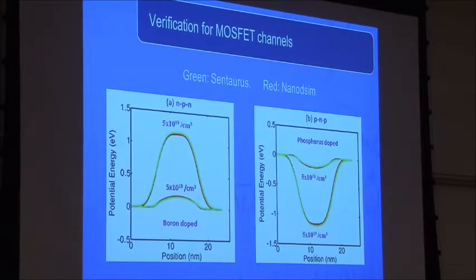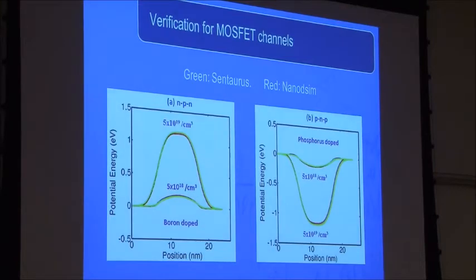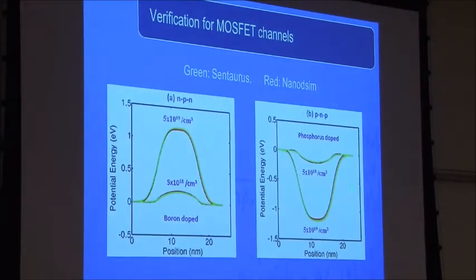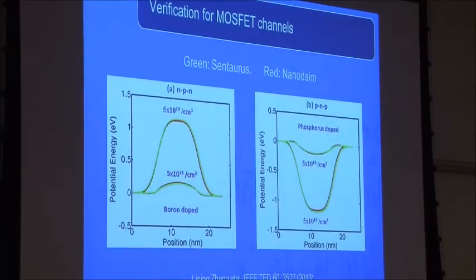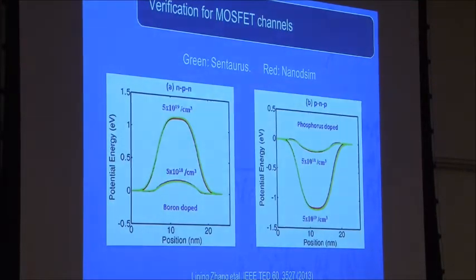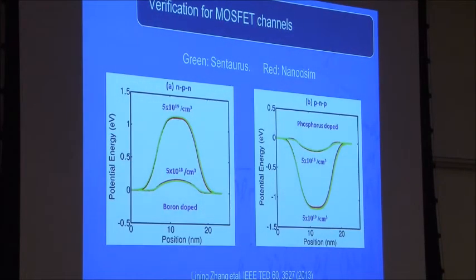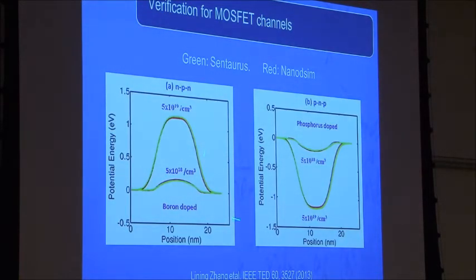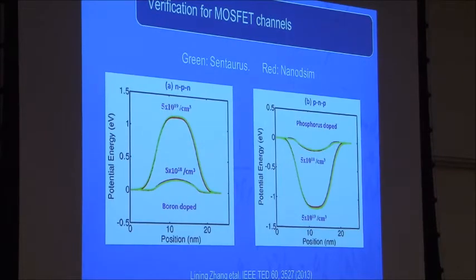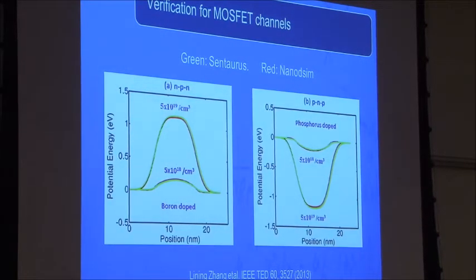And then we dope real atoms. This one we dope real boron atoms into our silicon. This one we dope real phosphorus atoms. And then after that doping, we have 2 different concentrations of doping using this CPA method. And we calculate potential. You see that these 2 agree quite well. Okay, there are some differences, but this is basically good enough, I think.